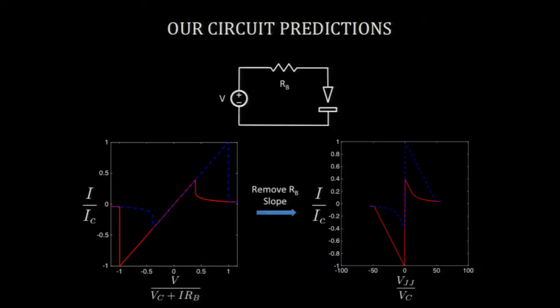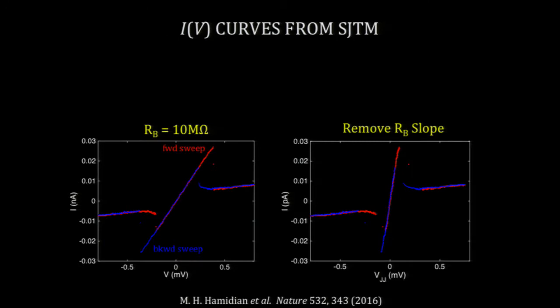So for our circuit, where we put in this little resistor, and this is our voltage source, we would expect to get this. So we took the old formula and just added one of these, and we got that. And if you were just to remove that slope, which is coming from the fact that you have this resistor, you end up with a curve like this. And if you measure what's at the top, this I_J squared will pop out. And so this is the data.